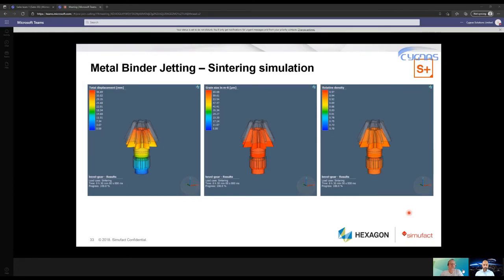And during the sintering, you have a very high densification of the part. You have a high shrinkage. But the shrinkage is not uniform, and that means you get a distortion while it shrinks. And this is also a challenge, but you can address this with simulation. So we can see the videos here, how the part shrinks, and this is unscaled, so it's scale 1. You have like a 30 to 50% shrinkage. You can predict that, and you can also do a compensation for this.